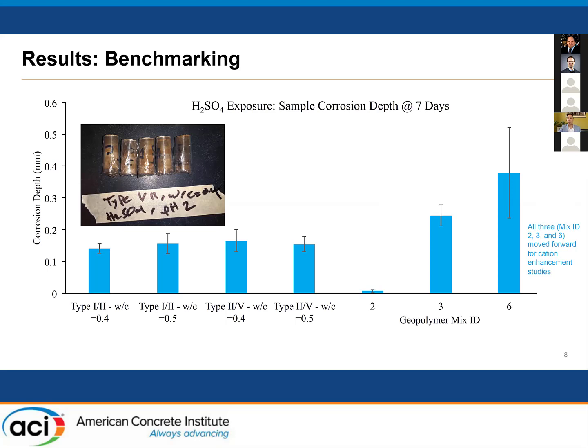In terms of the ordinary Portland cement controls, the type 1-2 samples provided the best performance. This is important because some folks might think that a type 2-5, which is a sulfate resistant cement, would perform better, but really resistance to sulfate attack, the exposure to sodium sulfate in groundwater, does not necessarily ensure resistance to sulfuric acid in sewers because it's an entirely different mechanism altogether. So really we found our type 1-2s to be better at resisting the sulfuric acid comparatively.